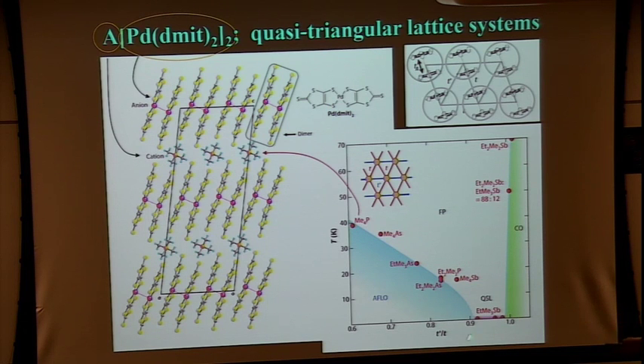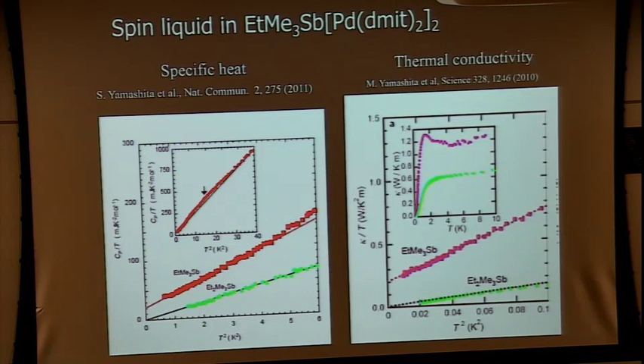So this is the Néel temperature, and the Néel temperature and the degree of frustration have a very clear correlation. As the frustration is stronger, the Néel temperature is suppressed, and then spin liquid occurs in these regions. The thermal conductivity and the specific heat measurements show very consistent results as far as these materials are concerned. The left side figure shows the specific heat. This is the charge ordered insulator, which shows a vanishingly small gamma as expected. But this is the spin liquid material.